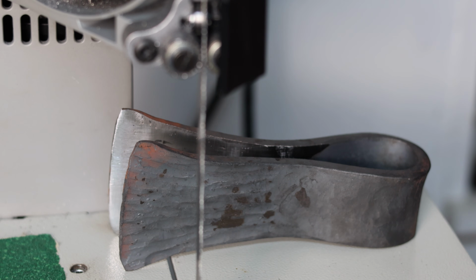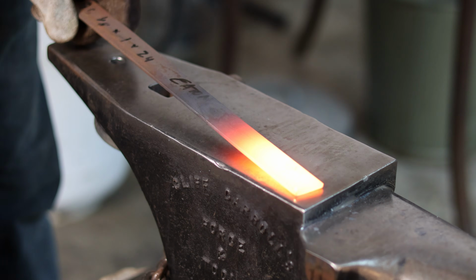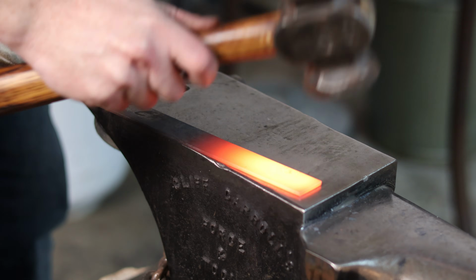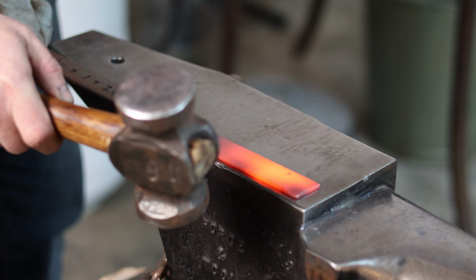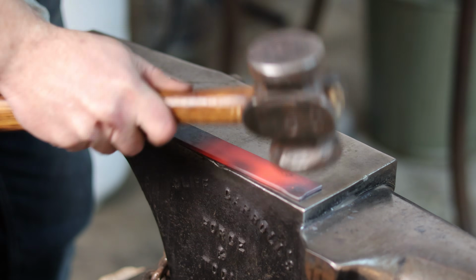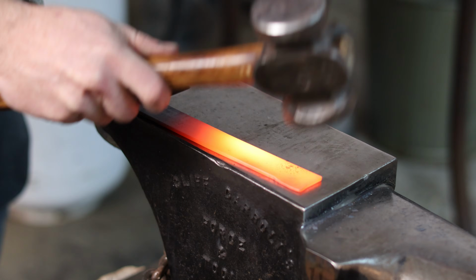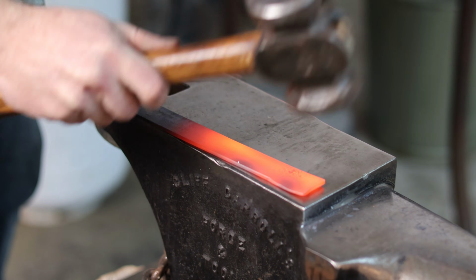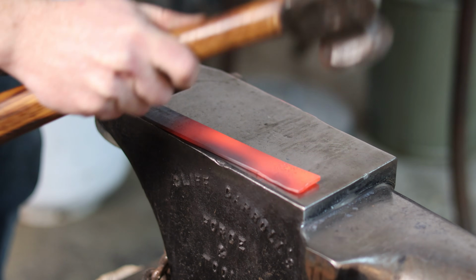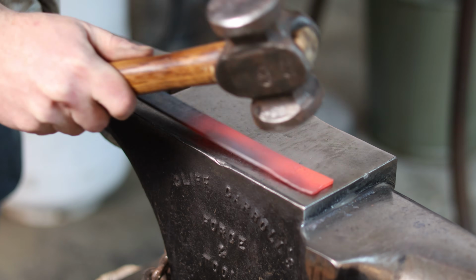All right, so now that I am done grinding that, we're going to go back to the forge and leave this here for a little bit. Now I've got a piece of 1 by 1/8 inch 1095, which is a high carbon steel that I'm going to spread out on one edge in order to prep this for the forge weld, and this is going to become the hardened edge of the Tomahawk.